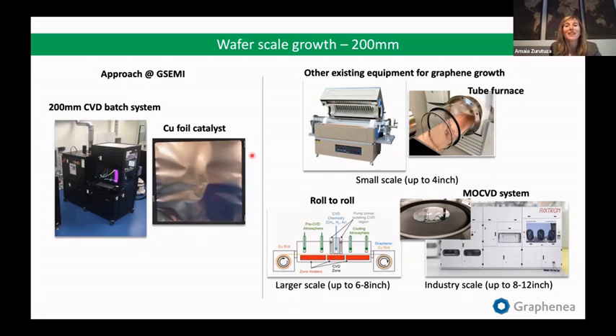We can grow 2 foils at the same time. So we introduce these 2 copper foils, we go to 1000 degrees, introduce methane, and we form this monolayer of graphene that is 0.345 nanometers in thickness, and is fully continuous. It is not single crystal because typically you have different nucleation spots, and the grains grow and finally merge to form these large films.